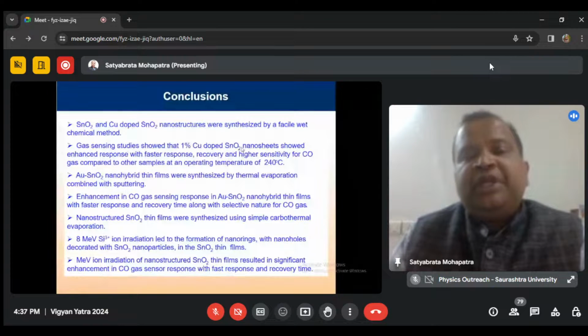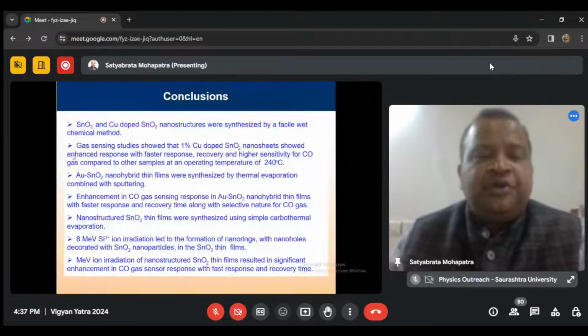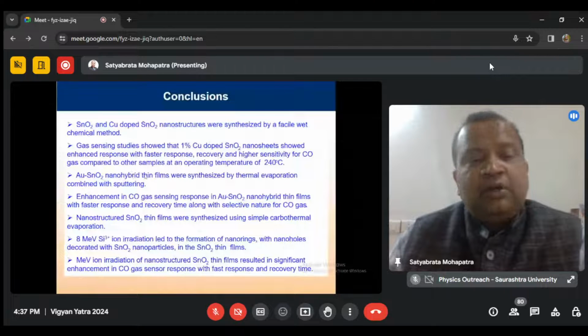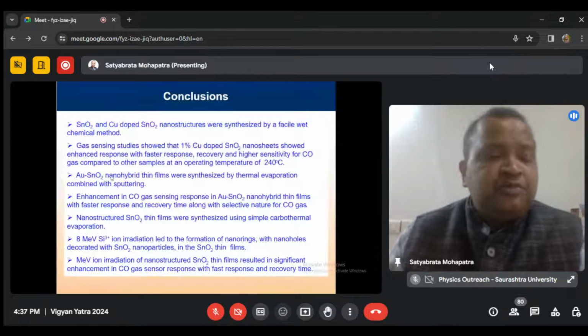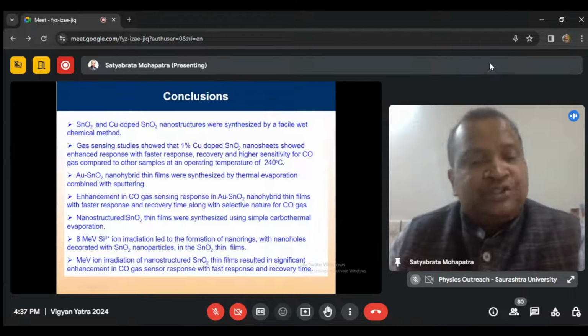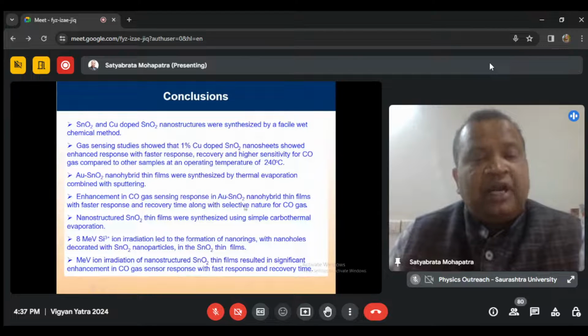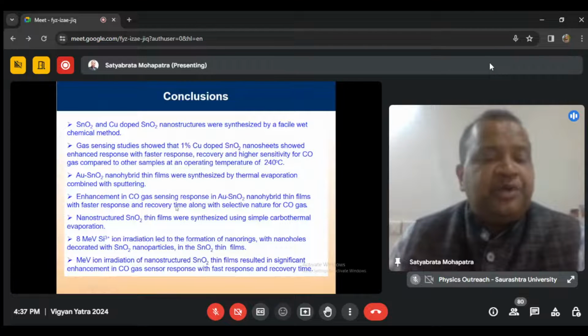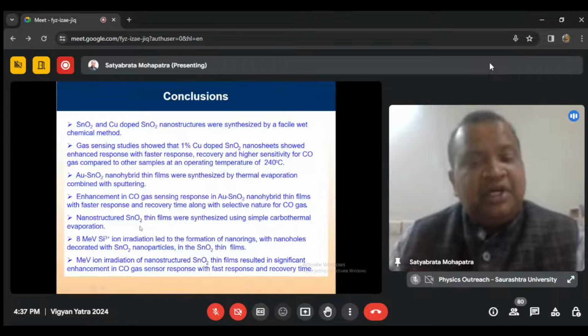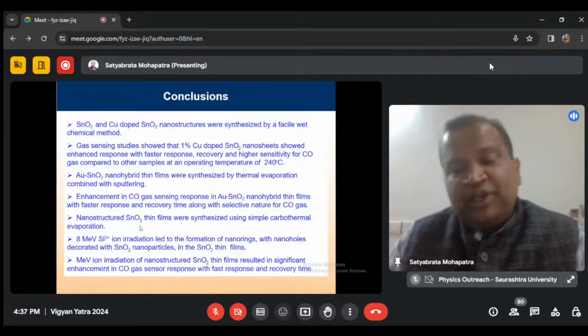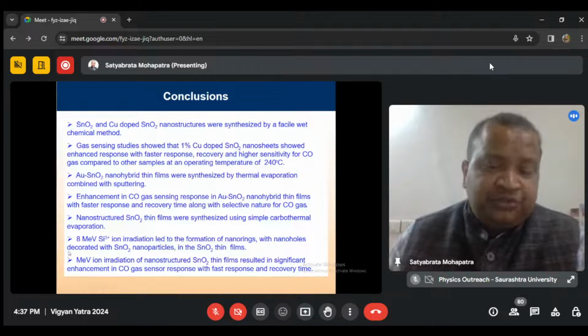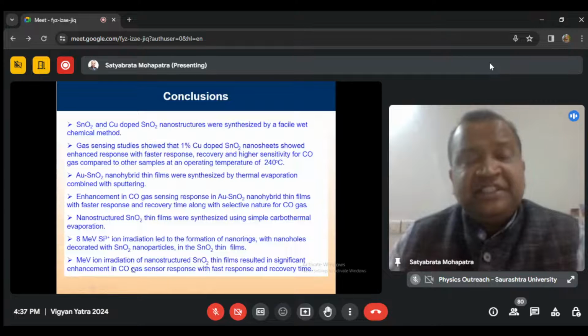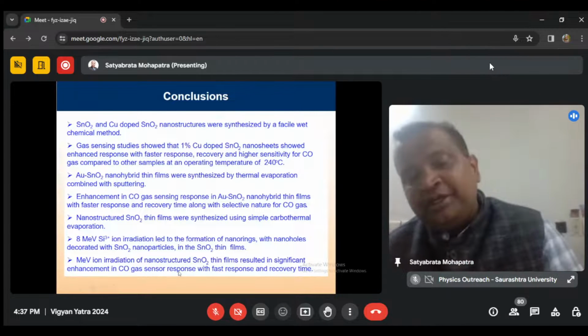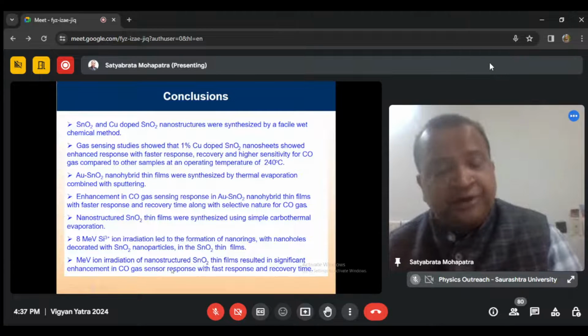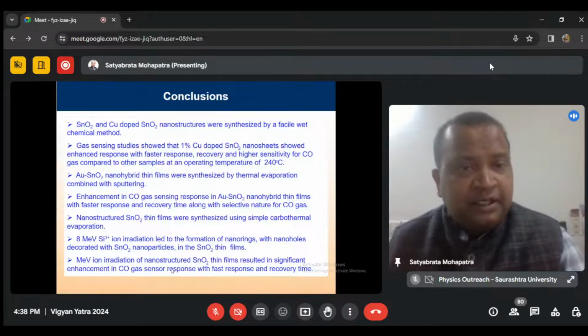So now, 1% copper doping in tin oxide nanosheets shows improved gas response with very small recovery and response time, and high selectivity, and gold-tin oxide nanohybrid. By producing these plasmonic nanohybrids, you produce hybrids of tin oxide nanostructures with gold, and that leads to improvement in the carbon monoxide gas sensor response. And of course, with very good selectivity and faster response and recovery time. Nanostructured tin oxide films can be engineered using ion beam into a film of nanorings. And this demonstrated significant enhancement, 16 times enhancement, in carbon monoxide gas sensor response with very fast response time and recovery time, paving the way for the development of smarter or efficient gas sensors with a planar geometry.